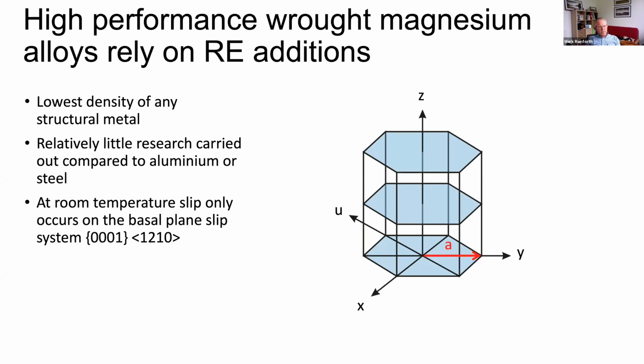Okay, so that's steels. Now for something completely different, I'll move on to magnesium alloys relatively briefly. Magnesium is around quite extensively as cast alloys, but wrought magnesium alloys are far less used. One reason is they tend to be quite expensive. A second reason is that they do rely on rare earth elements, because otherwise we will not get adequate formability.